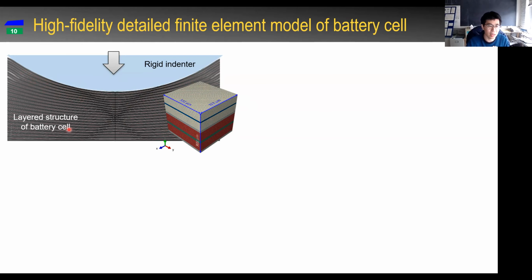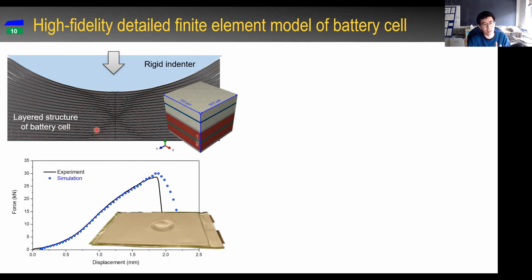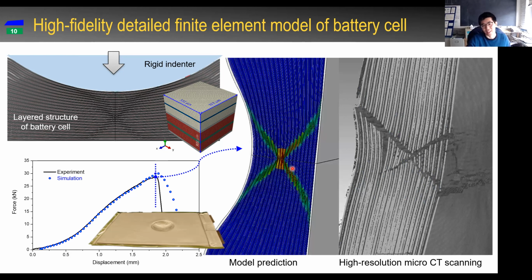And this is a simulation result of what we call indentation. This is the indenter, a rigid indenter, and the battery layered structure deformed in this way. We can see clearly there is strain localization here, which is very interesting. And we can also measure the force and displacement of this rigid indenter. Here the black curve is the test that we did on batteries, and the blue dots are simulation results. We can see quite a good prediction of the overall trend. There is some overshooting here, but that's because of the element deletion in the finite element model. If we look at this moment and cut the battery to see the cross section, we can see clearly a very interesting X-shape fracture, and our model can definitely predict this. To us, this is a very exciting achievement about the solid skeleton.